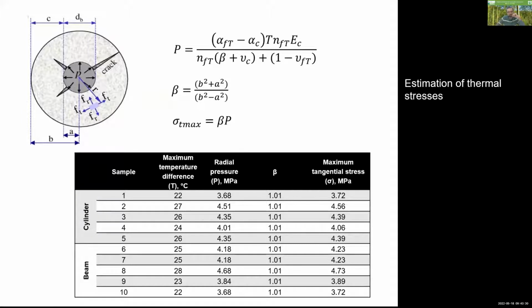We also developed some models to predict all those bonding behaviors, especially in terms of thermal stresses. That was a very important factor because the thermal expansion coefficient of bamboo composite or engineered bamboo is very different from steel and concrete, and that could definitely cause an issue when we use it in an environment where we have a really huge difference between the thermal conditions of the outside and inside of the concrete samples.